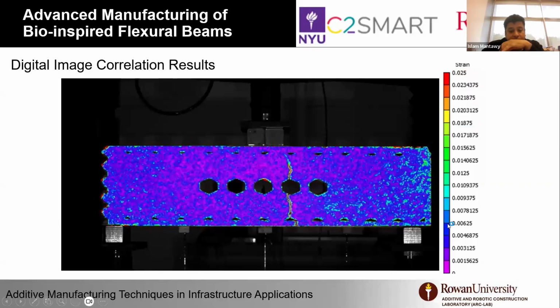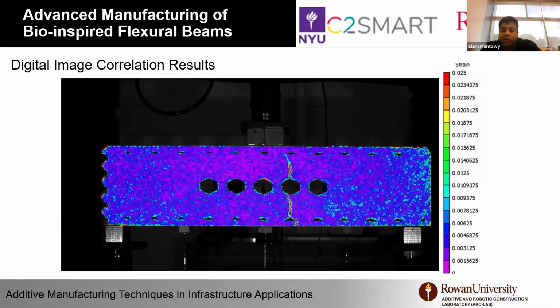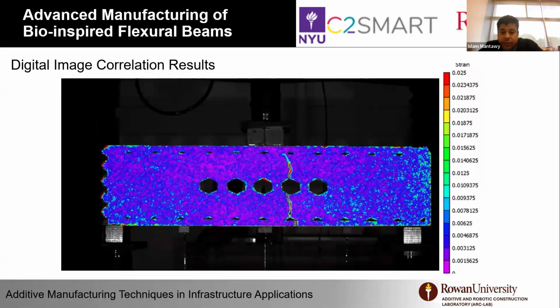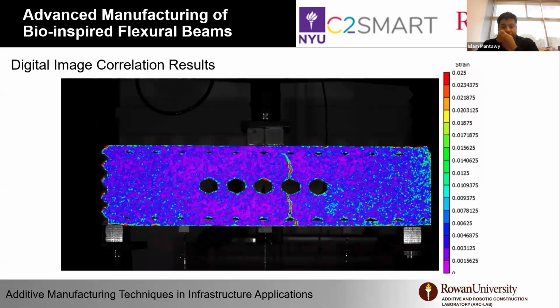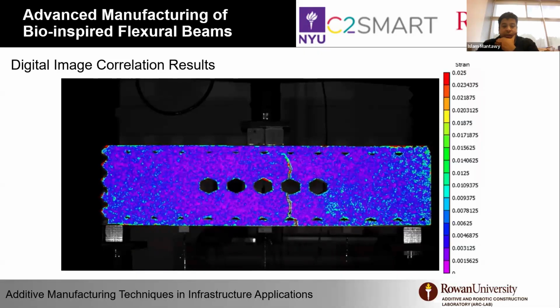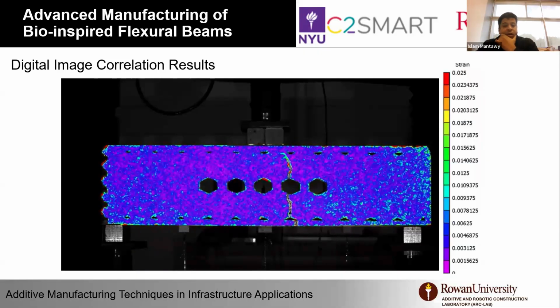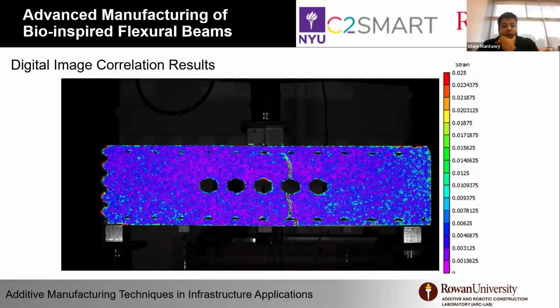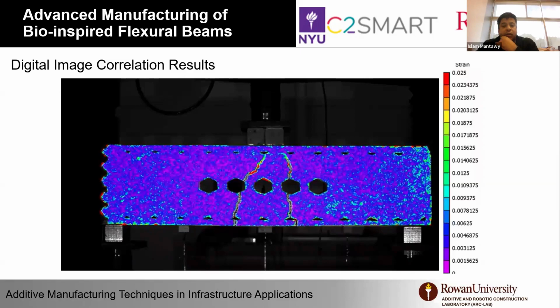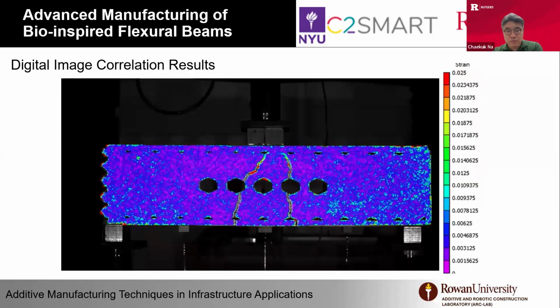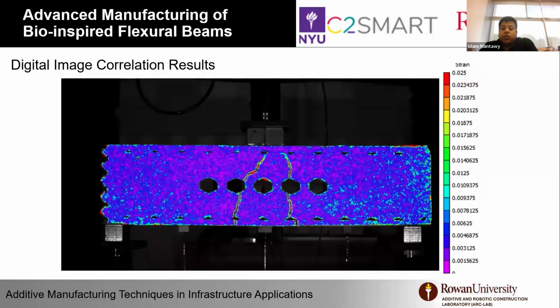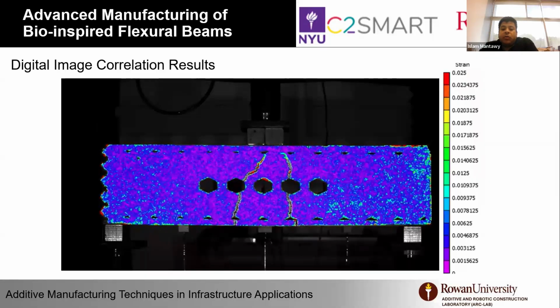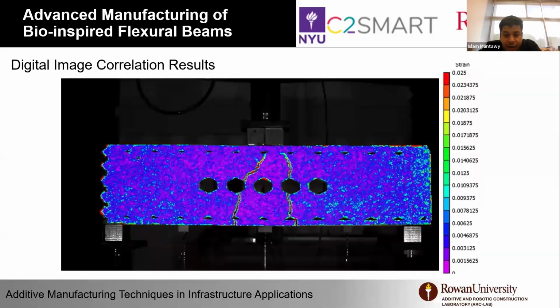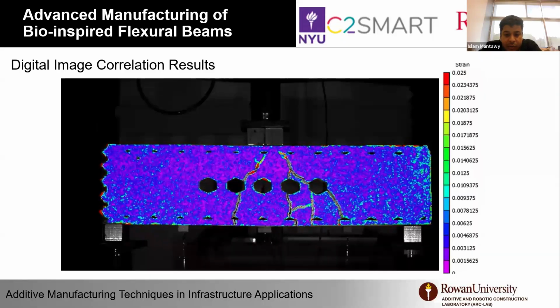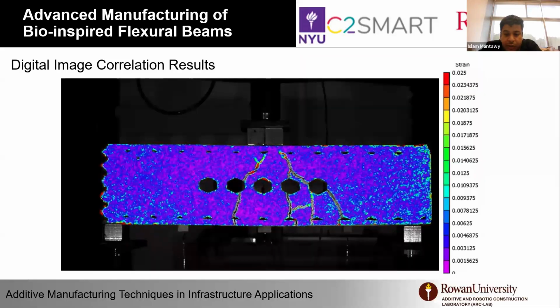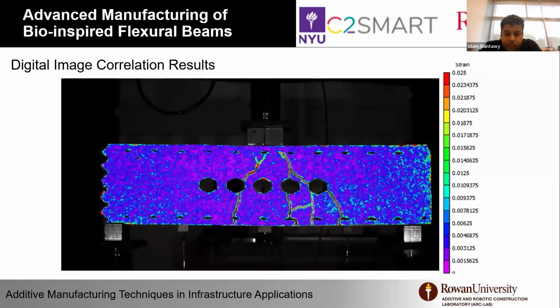Yeah, so basically what we have done is we have the digital image correlation equipment, where we spray the surface and create a random speckle pattern, so that with cameras you can correlate the movement of the speckle pattern. It's only a surface measurement, so it shows you the principal strain on the right side as you load the structures. So basically, when the crack forms, you lose those patterns, so there are the gray lines here, but outside of that, you can start seeing the evolving strains using the high-speed camera.